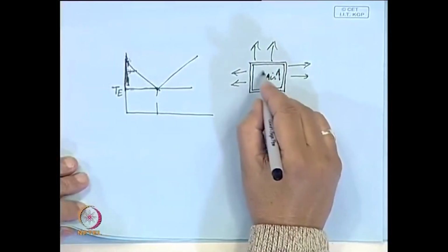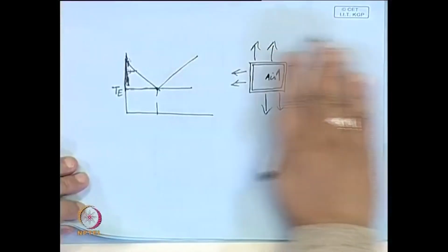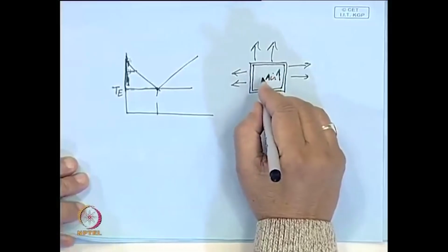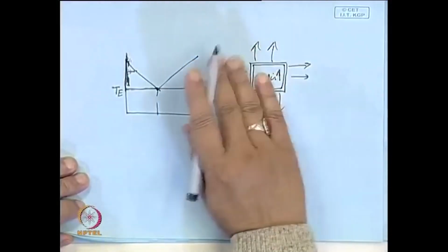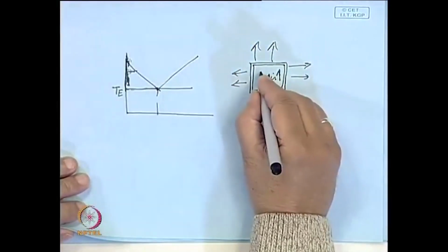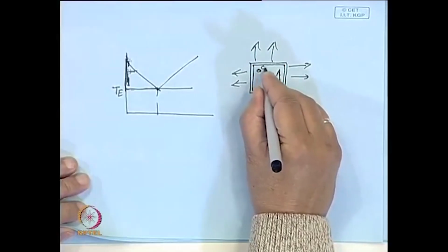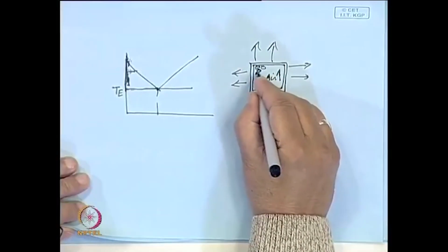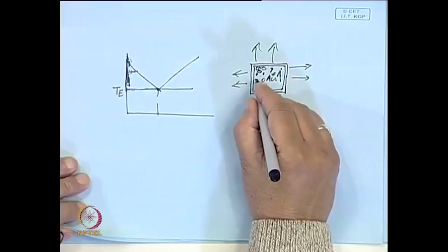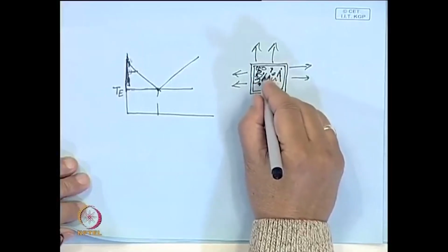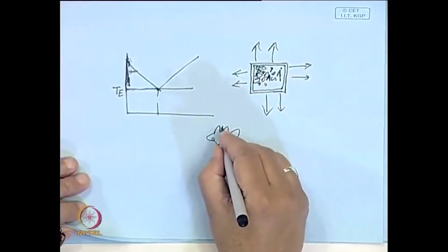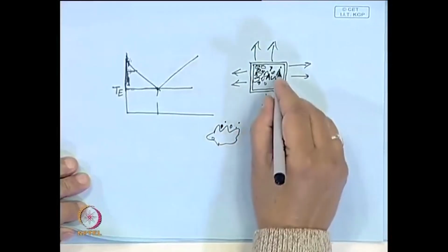solidify together. That means ice will form, but in the meantime a crust will form on the top of the ice, because heat will be extracted from the top as well, and the ice is lighter. So, therefore, ice puts a cover, and this air which is trapped is also not able to come out. So once these ice crystals form here, the air bubbles will also get entrapped between the dendrites of ice, these are crystals of ice, and in the channels between the crystals there will be air bubbles, and this is what you see.